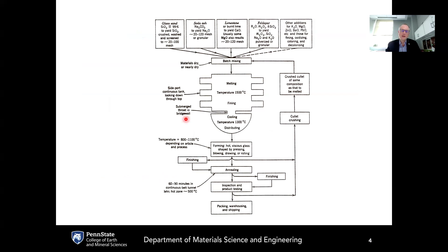This shows a schematic diagram of a typical industrial glass forming process, where you've got bins that contain different batch materials — such as quartz sand, soda ash, limestone, and feldspar. They are brought into the factory and go into a batch mixer where they are also mixed with cullet. So if you're making soda lime silicate, the cullet would be soda lime cullet and would get mixed with the quartz sand, soda ash, and limestone for a thoroughly mixed batch to aid in homogenization of the glass melt. This batch then gets fed into the melter at a controlled rate, because the rate of batch material going in must be commensurate with the rate of glass being produced at the other side.